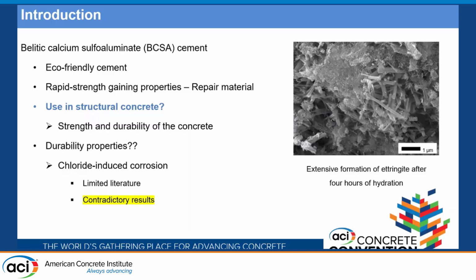There are two issues we need to address in this category. First, there is limited literature available on the chloride corrosion and chloride studies of BCSA cement. And second, there is contradiction among the results. Some researchers say that BCSA has poor corrosion performance, whereas field investigation has shown no signs of corrosion even after 23 years of service life and despite being exposed to de-icing salts.